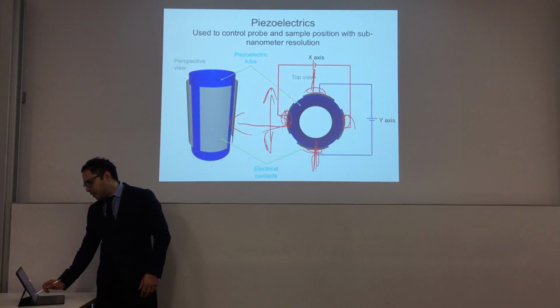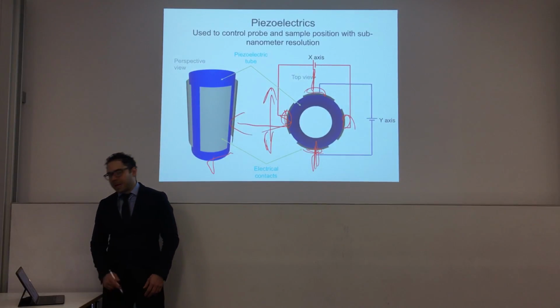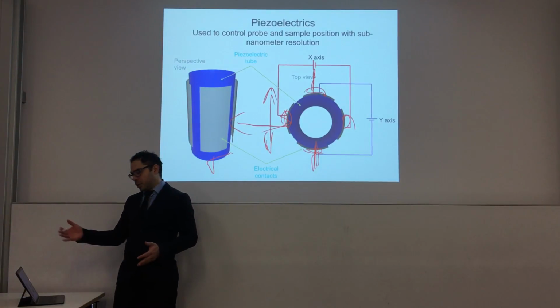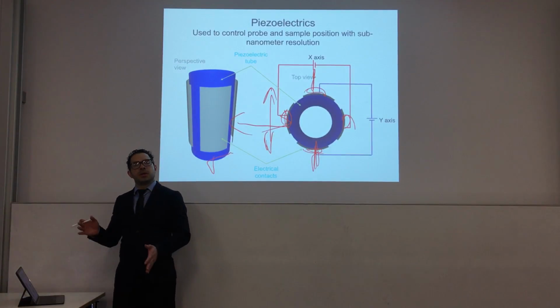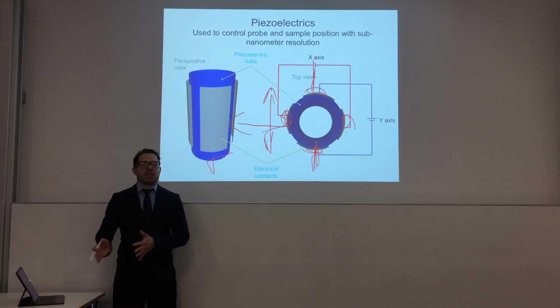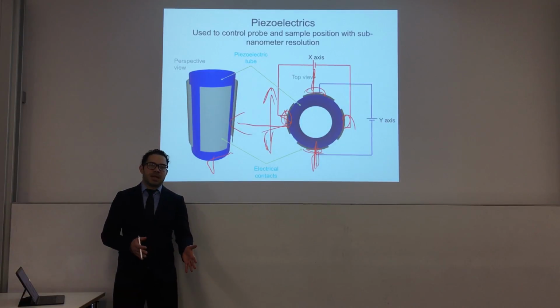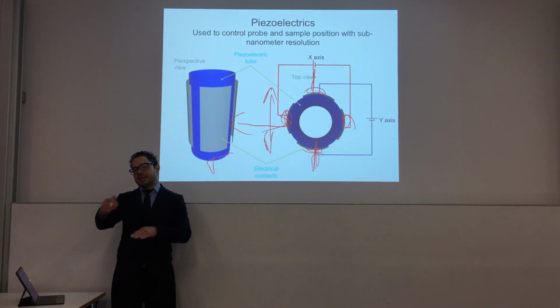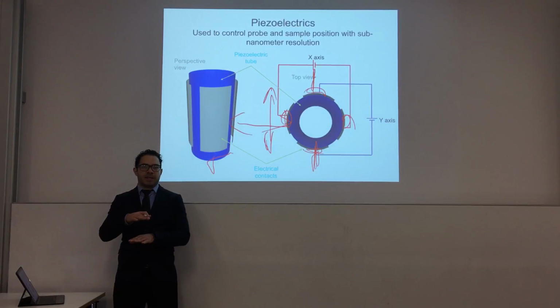So if you have a tip at the end of your piezoelectric tube, a cantilever or an STM tip, you can use this potential to scan the tip on the sample. And also, of course, you can have a stacked tube on the vertical axis to apply a potential difference in that axis to control the tip-sample distance.